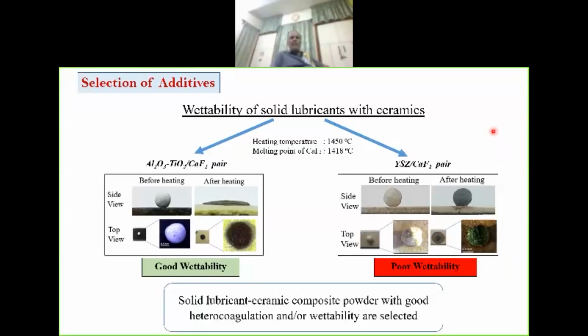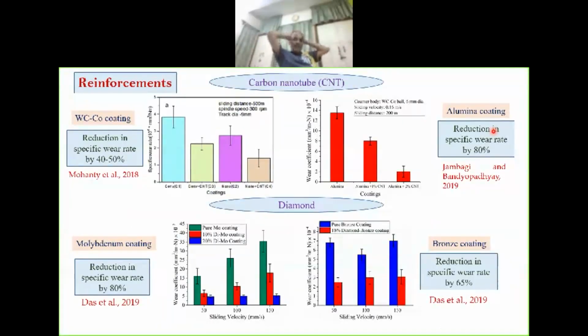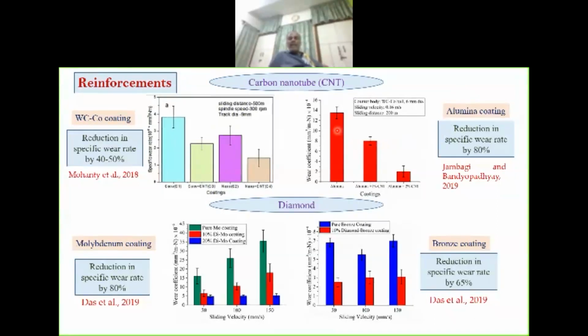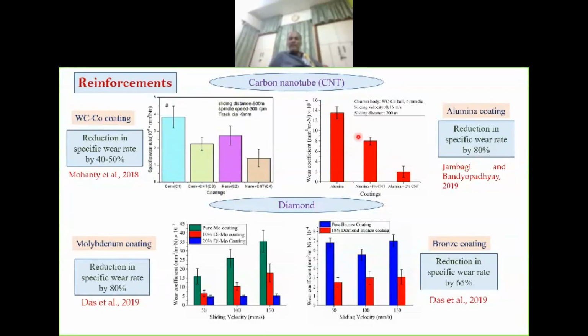Now, after doing the composite coatings, what do we do? What kind of improvement do we get? Here you see, I have a simple tungsten carbide. I put some CNT into it. The wear coefficient is a measurement index of wear, how quickly material is removed. That reduces, wear resistance increases. In each case, this is one type of carbide, this is another type of carbide, we get a reduction. With aluminum oxide also, we get reduction. It increases with percentage of carbon nanotube. But we cannot increase carbon nanotube indefinitely. That will create some other problem in powder flow. 2% gives me very good results. Okay.